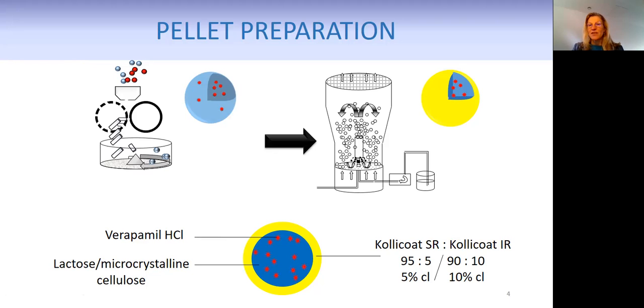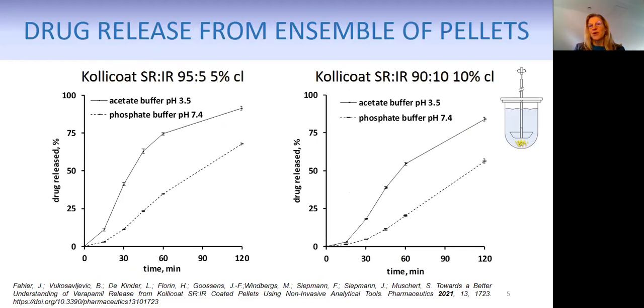So we used two blends. The first one is a 95-5 blend with a coating thickness of 5% weight gain or coating level. And the second blend we tested was a 90-10 blend with 10% weight gain, 10% coating. So here you can see the drug release from these coated pellets performed in a USP paddle apparatus, a standard dissolution procedure. The drug release was always faster in acetate buffer, pH 3.5, which is actually not a physiologically important medium, but for technical reasons, we chose a pH 3.5 and a pH 7.4 medium.